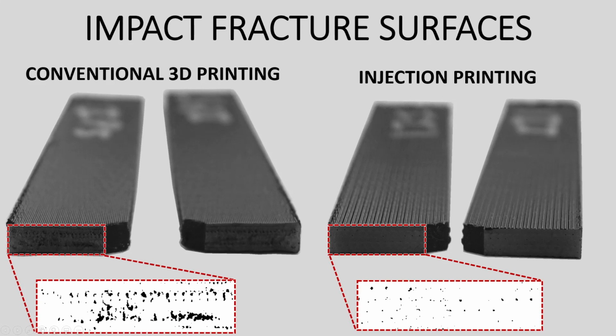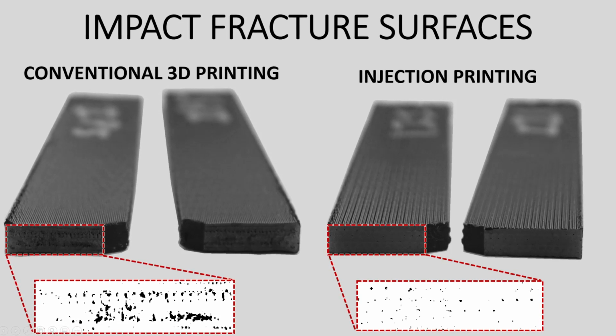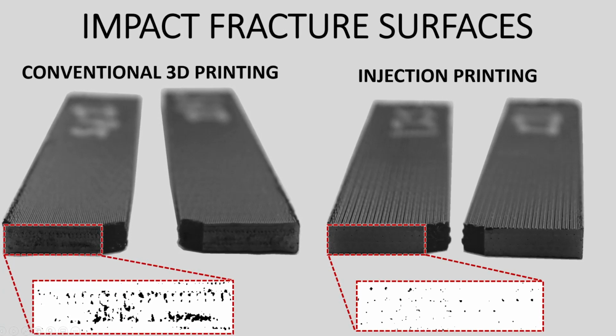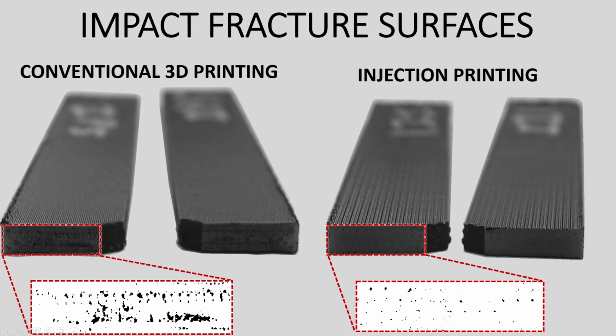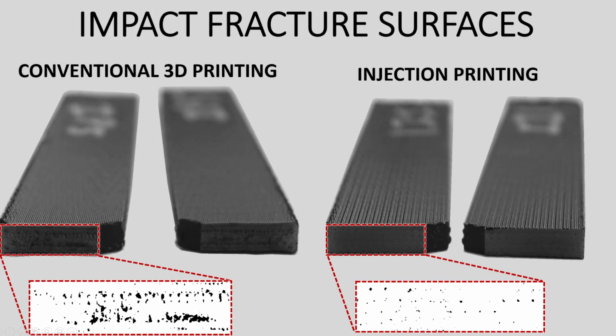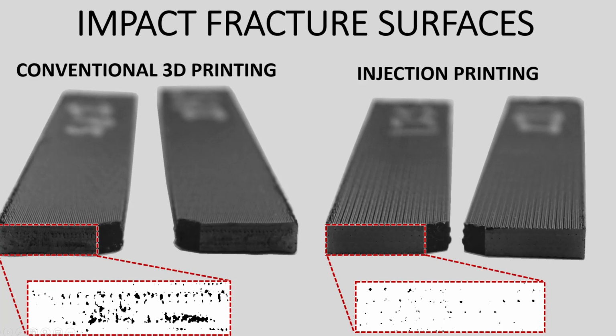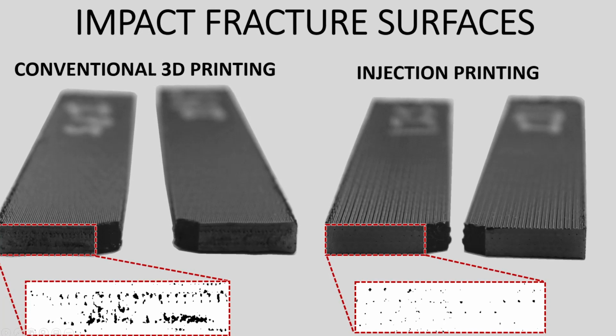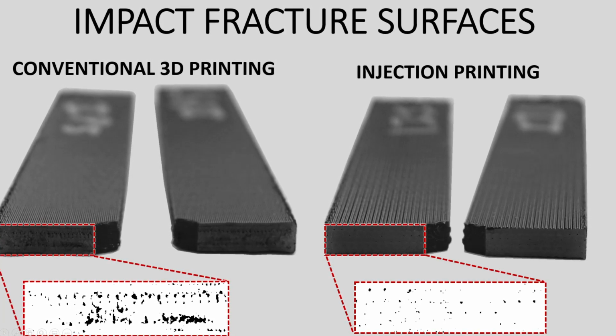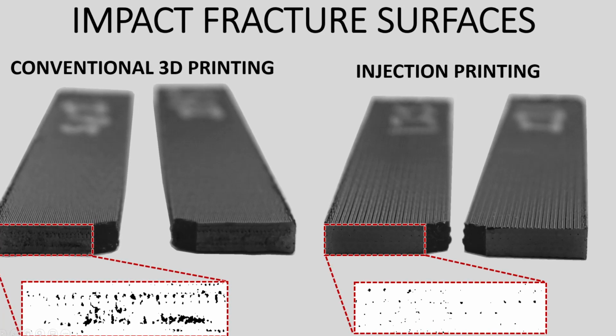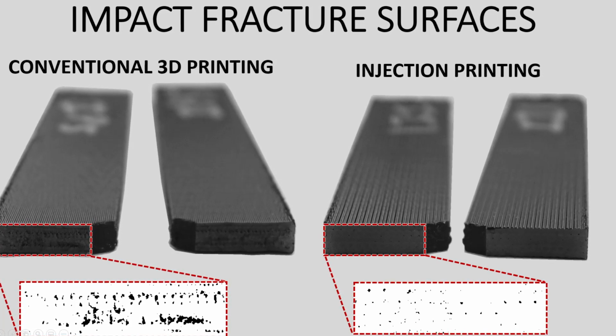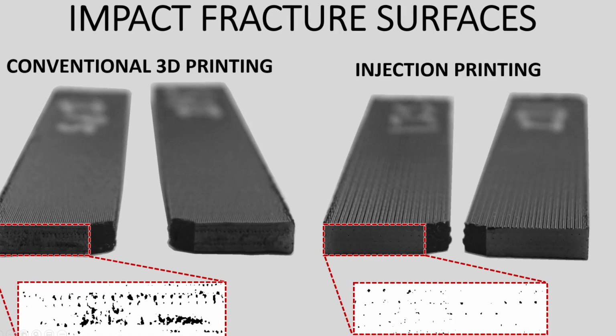There are two main reasons for the increased part strength. First, the parts are much more dense than typical 3D printing, since the injected melt tends to fully fill the cavities between the shell walls. Second, the injected melt provides much more thermal mass than a typical road, allowing the weld interfaces between the injected material and the surrounding shells to fully heal.